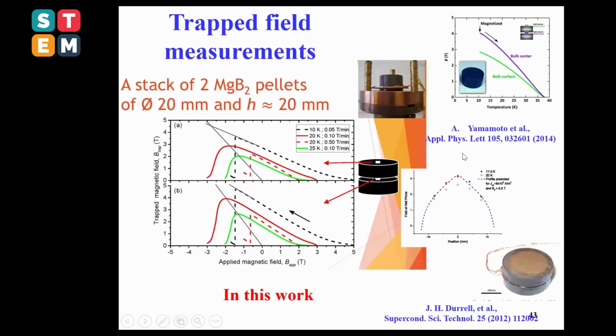Well, how about the trap field? Because as I'm saying, the work for us was to prepare the cryomagnet samples. You can clearly observe here in our sample, a 20 mm sample where you put two hall sensors between, you were able to trap, like you can clearly observe in that case, roughly 4 Tesla on top of the sample. But you should just take care about the speed of the magnetic field that you apply, because if you cannot control this, you will observe such a kind of flux jump, like you can clearly observe in this dotted curve here.